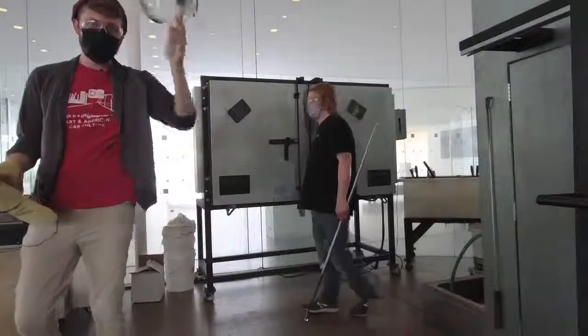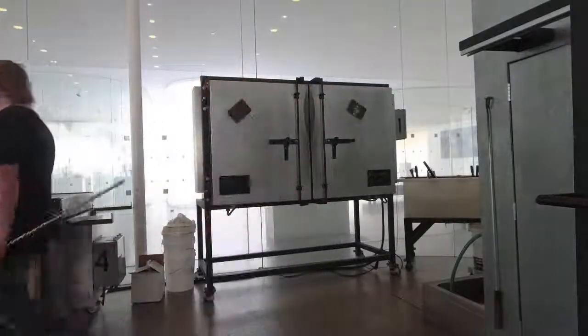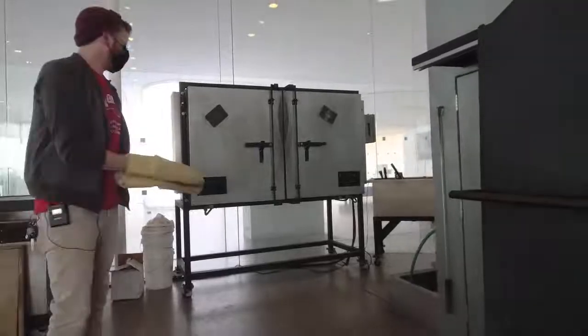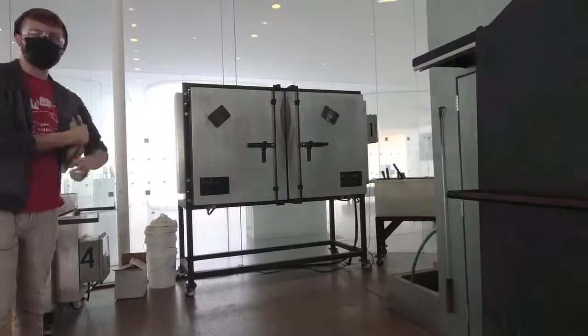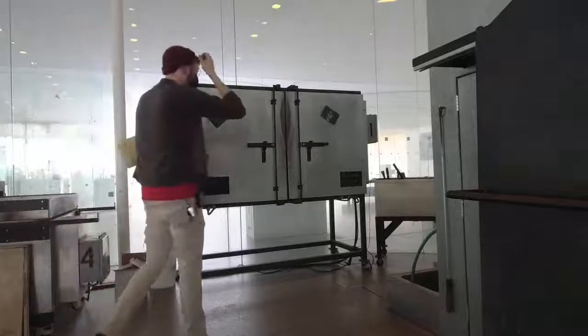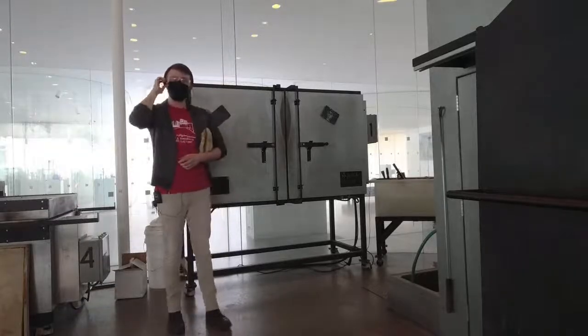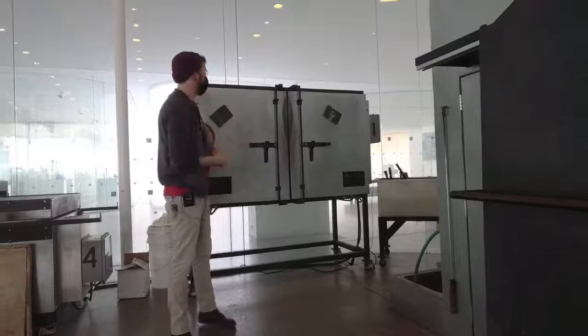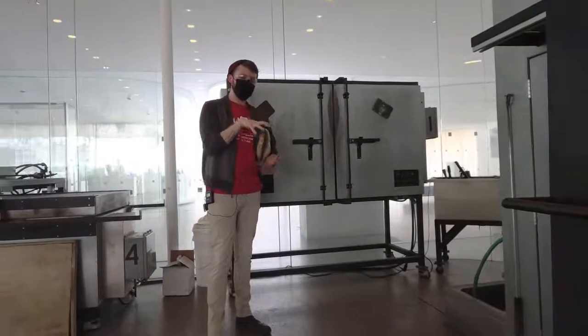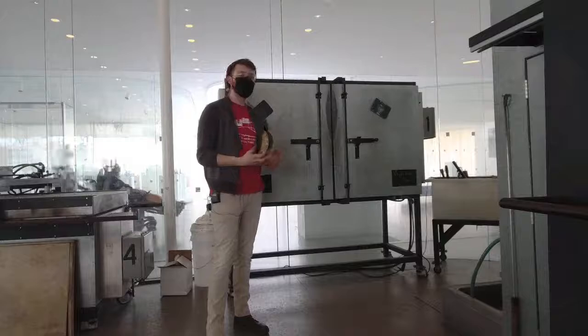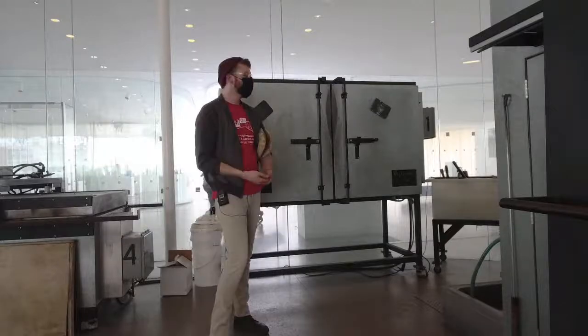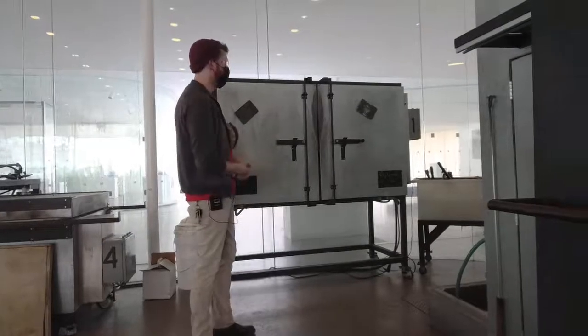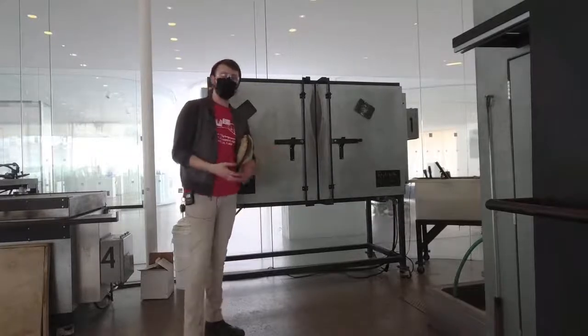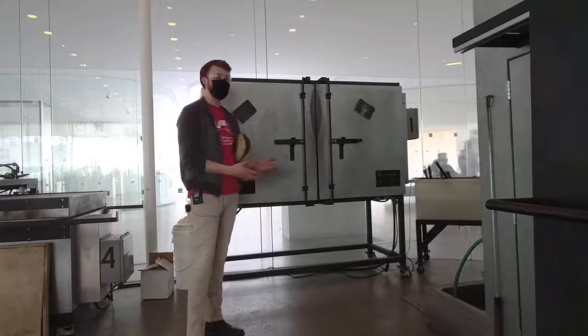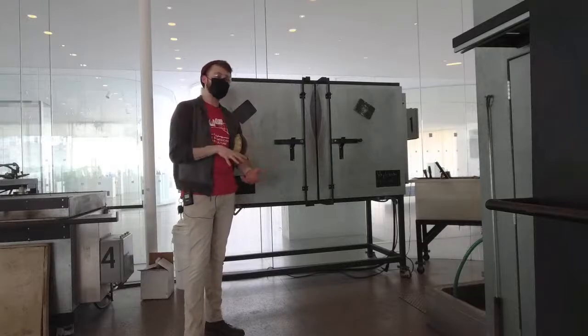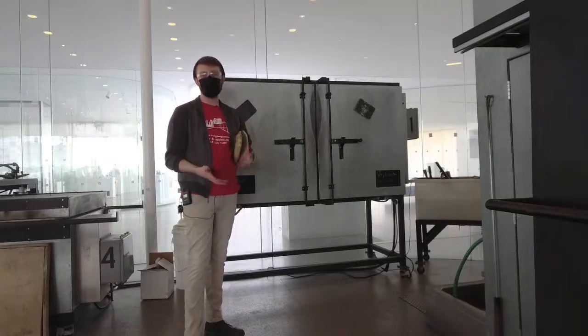And now it's safe inside of our annealing oven. So the process of annealing is basically just allowing the glass to even out in temperature. It's holding at 918 degrees. And like I said, that's a really stable temperature for the glass to rest at. It doesn't heat up to the point where it's going to slump and deform, and it doesn't cool down to the point where it could induce any thermal shock. So it could rest there for a while and go relatively unchanged, but we want to get it out as soon as possible. So at the end of the day, we're just going to press a button in our control panel, and it's going to slowly ramp down over the course of about 16 hours or so.